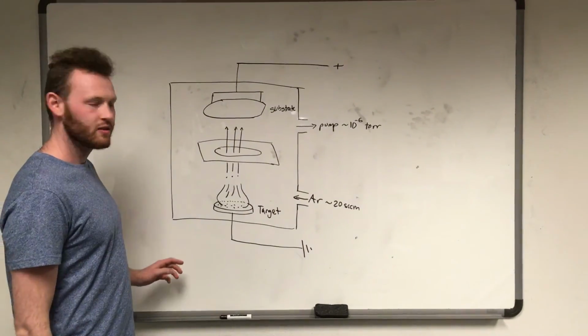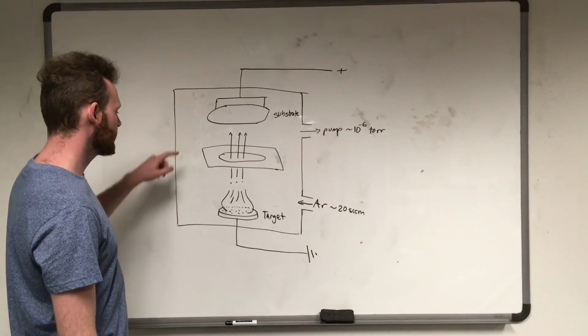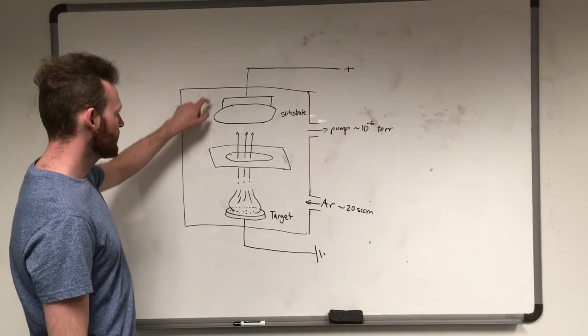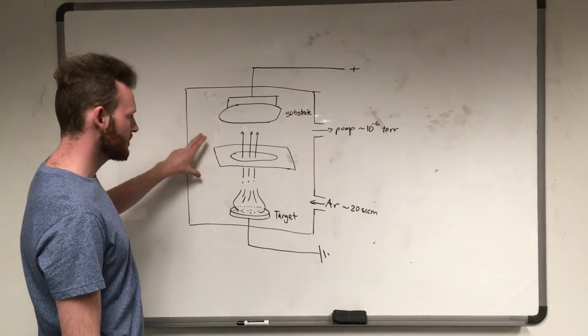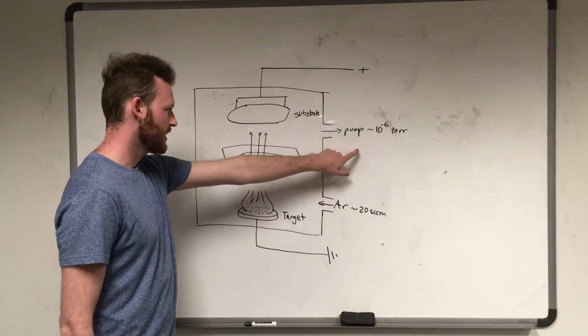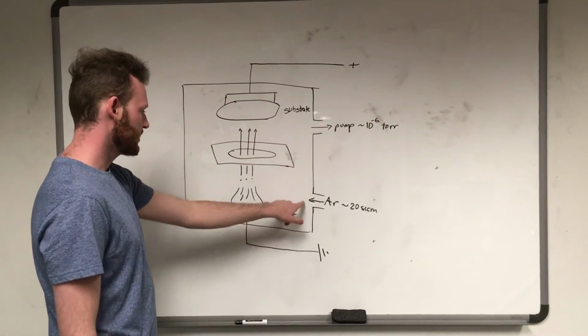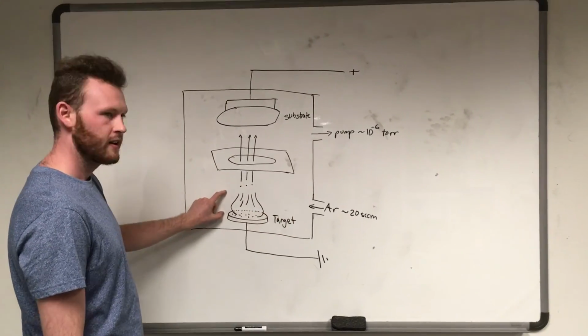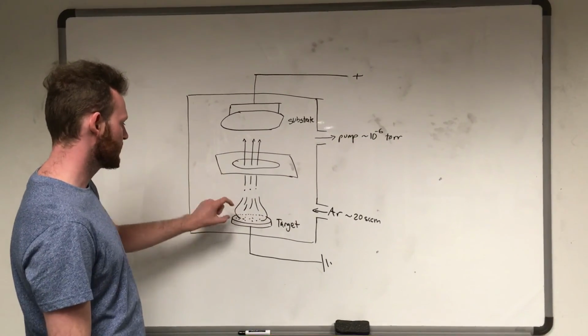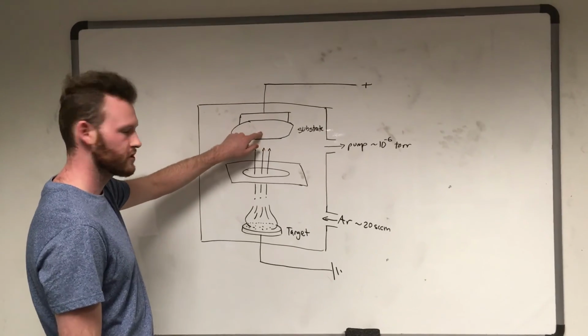This is a schematic of the sputter deposition chamber. We have a target and a substrate with a large electric field in between them. The chamber itself is ultra-high vacuum, 10 to the minus 6 torr, and we inject a tiny bit of argon to induce a plasma. And that plasma rips off atoms from the target surface and deposits it onto the substrate.